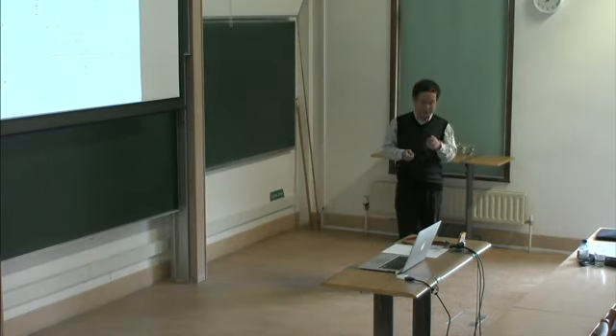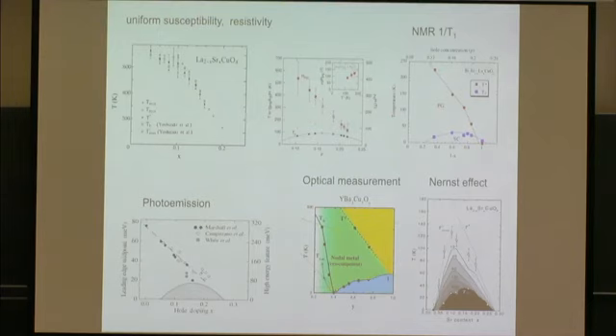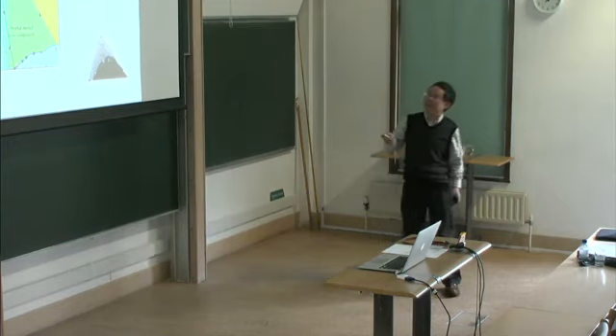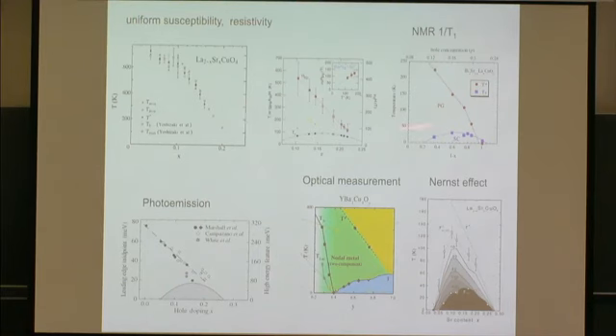And in fact, in the past 2 decades, a lot of experiments have been done with all different kinds of approaches: transport, uniform susceptibility, NMR, photoemission, optical, Nernst effect, and other measurements. They show systematically that above the superconducting dome, you have some kind of pseudogap behavior. But notice that the temperature scale is quite different for different measurements.